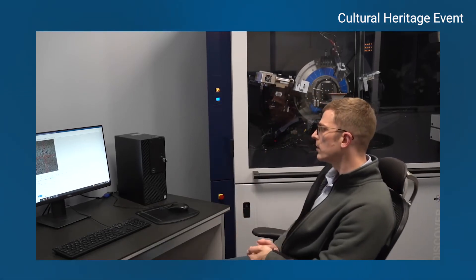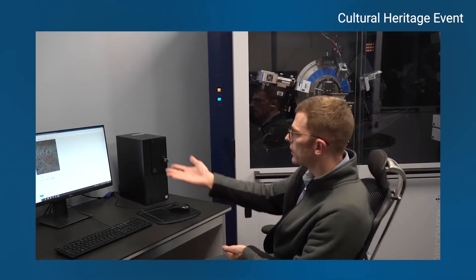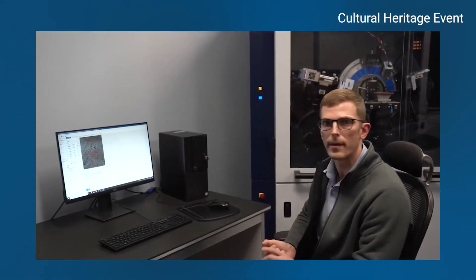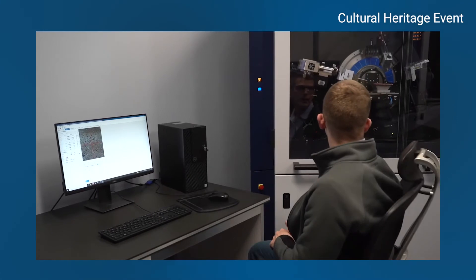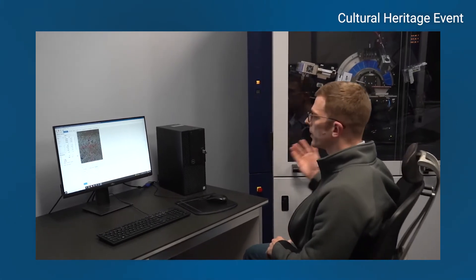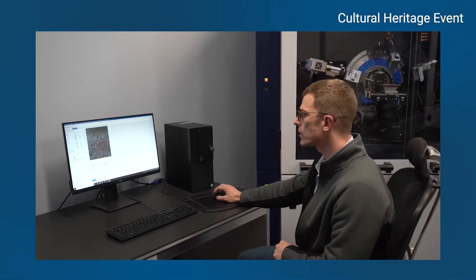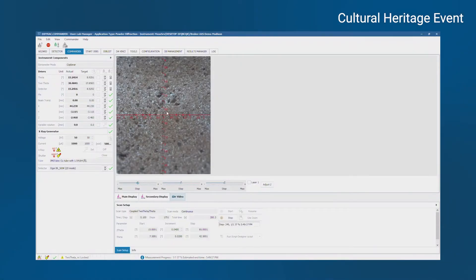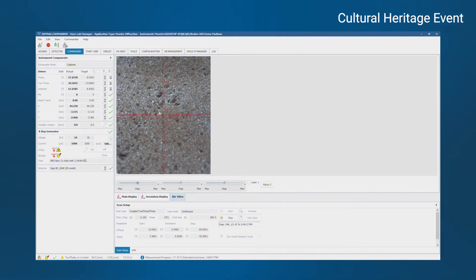Right now I'm not really targeting a small area. You can see it fills the camera image just with the bare ceramic. But I have a one millimeter collimator. So all the diffraction information is coming from this very central region in between the first hashes. This is 0.5 millimeter hashes on the reticle. So this is where the diffraction information is coming from.